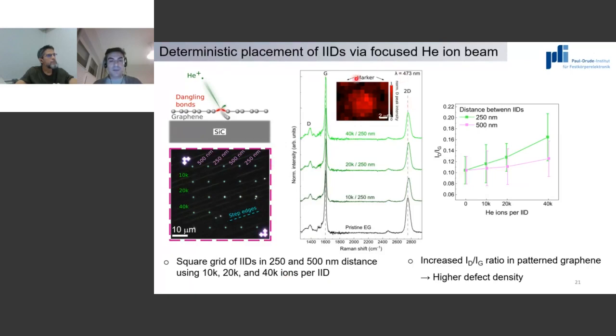I'm just showing that because then we do some Raman mapping around one of these squares. It's difficult to see, but the markers are here in the corner, and in the middle is where we have this pattern of defects. Looking at the Raman results, we see the trend that the intensity of the D peak, which is related to defects, is increasing. This should be so because we are putting in defects, and you see in the mapping that the D peak intensity is increasing around this area as we expect. So good news, this helium focused ion beam can generate defects.